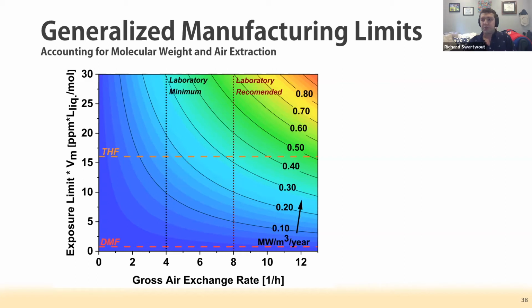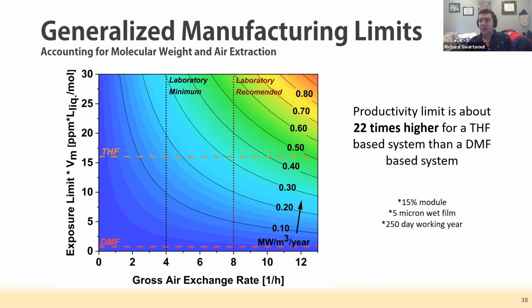Moving from something relatively toxic like DMF to something a little more benign like THF, which is used pretty commonly in epoxy-based coating systems, you get about a 22 times higher productivity ceiling than the traditional toxic solvent commonly used in perovskites.